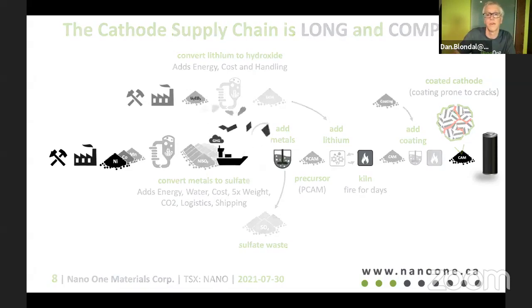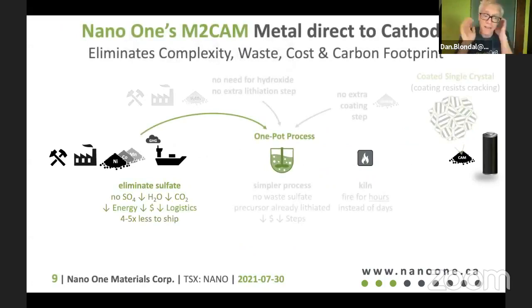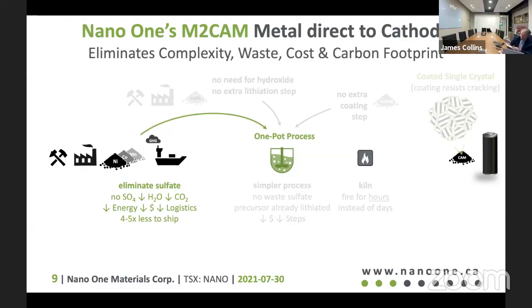we actually completely eliminate the need for sulfate. And so we bypass the sulfate intermediate step, and of course that completely eliminates sulfate. It cuts down the amount of water, cuts down the carbon footprint because you don't have to ship as much material around. You're not using all that energy to make the sulfate or ship it. And that, of course, has an impact on cost and logistics as well.